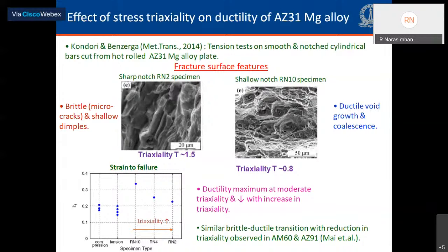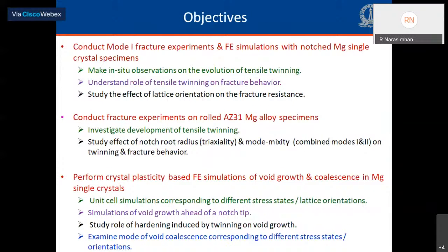Now, similar brittle to ductile transitions with reduction in triaxiality have also been observed in other magnesium alloys like AM60 and AZ91. Now, with that little introduction, let me turn to the objectives of our work. Since tensile twinning, essentially, although contraction twins are also important, have been shown in the literature to play a very pivotal role in the deformation and failure in magnesium, we wanted to understand this more closely. So we wanted to begin by doing fracture experiments using magnesium single crystal specimens and understand how tensile twinning develops and what's the effect on the fracture resistance.